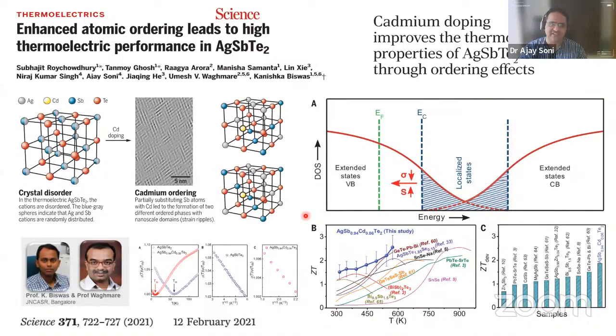We also worked on some other materials like AgSbTe2 with Professor Biswas and Professor Waghmare, the recent work which was published in Science last year. These are the chemists, so they create the samples as per the demand, as per the desired. So here the interesting aspect is that when you dope something, you create a disorder. But when you dope or put something in, if it increases the orderness in the material, that's the exciting science. So with this particular material, with 6% Cd doping or something, AgSbTe2 gives rise to more ordering in the material, which gives good electrical transport and poor thermal conductivity because you are putting the cadmium into it, which can create the phonon scattering center. And now you can see the ZT for that particular research is almost 2.5 or something. This is extremely high, and the science is very interesting, so that's why it is published in Science.